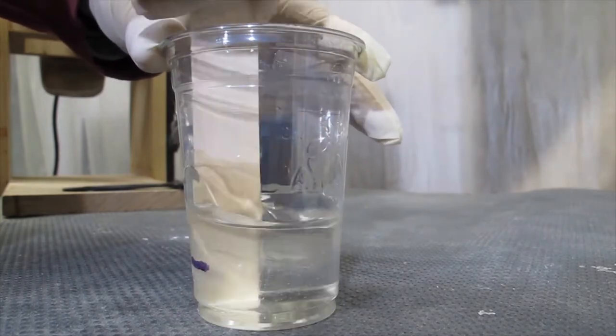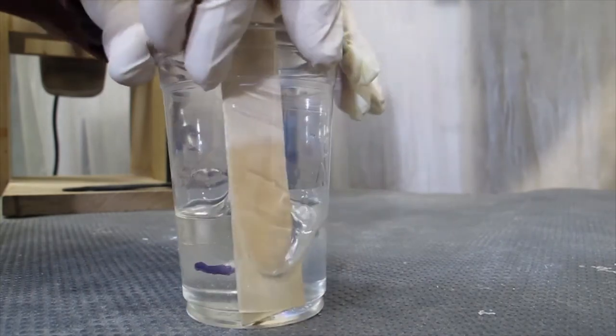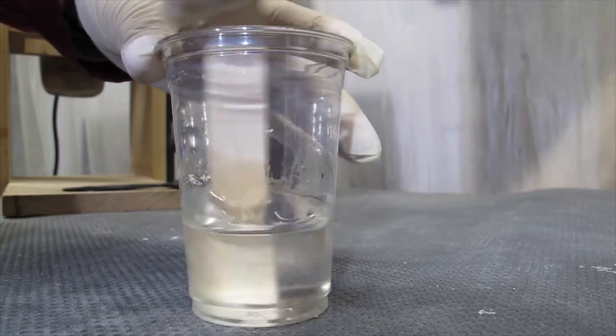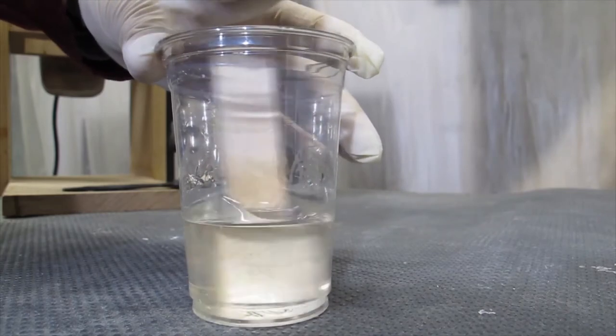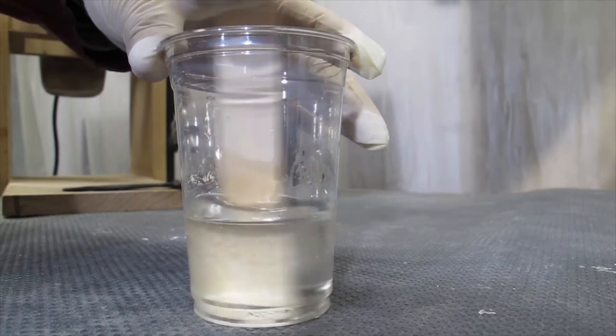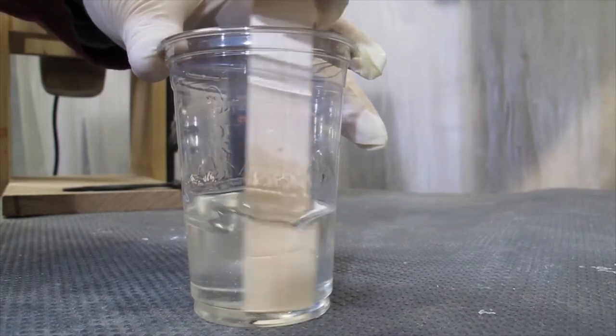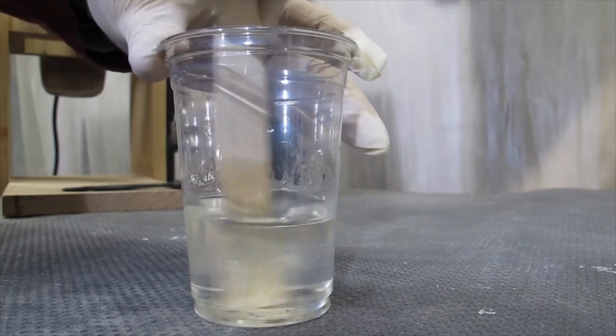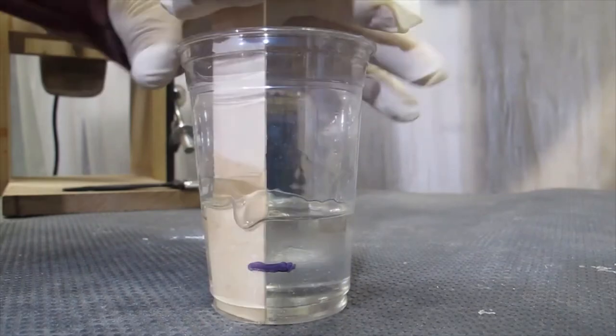The resin I use has a 30-minute pot life at room temperature. The larger the volume of resin that you mix, the faster it will cure. Because it is thermal setting, the higher volume produces a higher temperature and it sets faster. You can see that it is getting clearer.